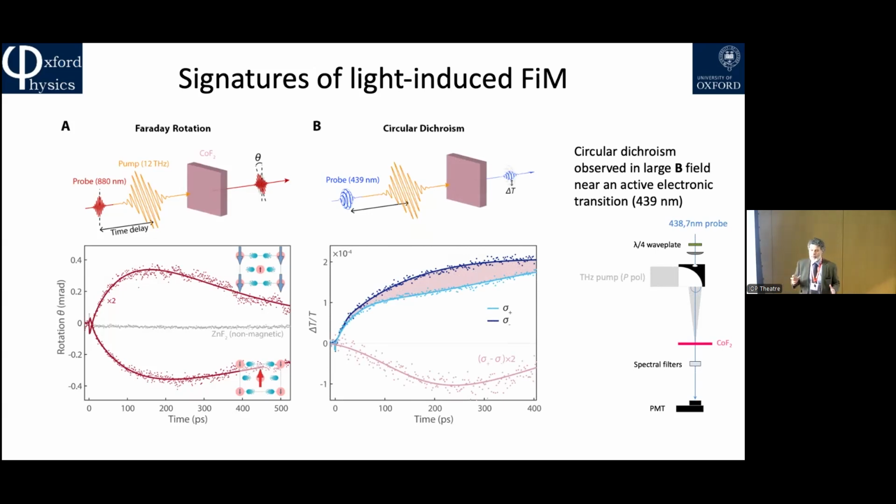Now, this is profoundly weird and profoundly counter to the kind of adiabatic picture. Remember, what we said is that we were pumping up the phonons. The pump pulse is less than a picosecond. Then these phonons propagate relatively slowly, but the lifetime of a phonon polariton is typically 10 to 20 picoseconds. So the whole oscillation in the crystal only lasts 20 picoseconds. Now you have here a response that lasts for hundreds of picoseconds. So it cannot be, and this is an experimental result, due to the fact that there is an oscillating phonon field in the material. There's got to be something else that you have created.